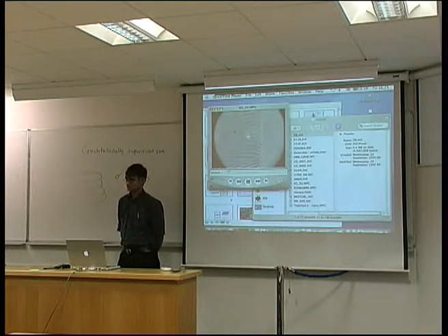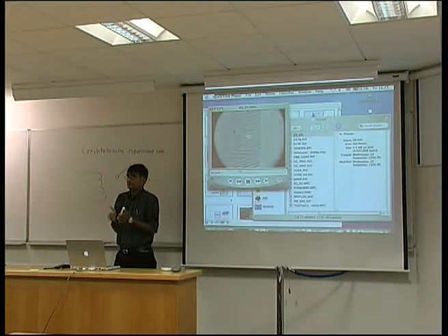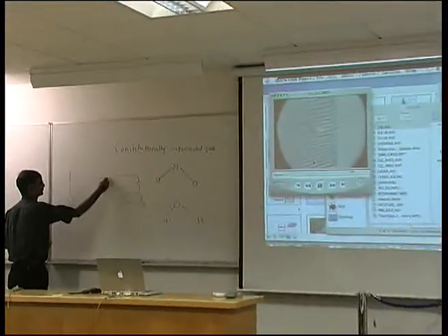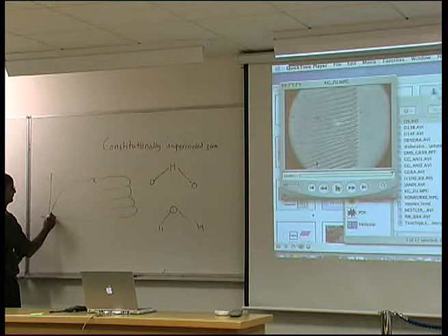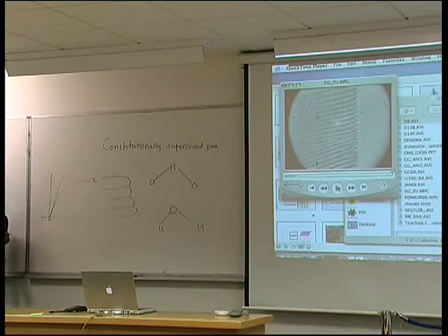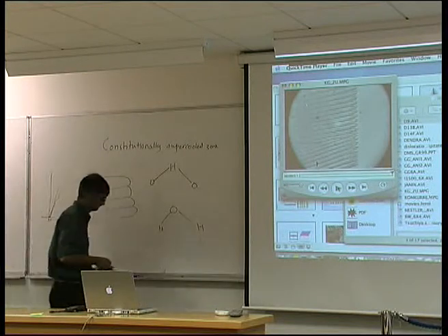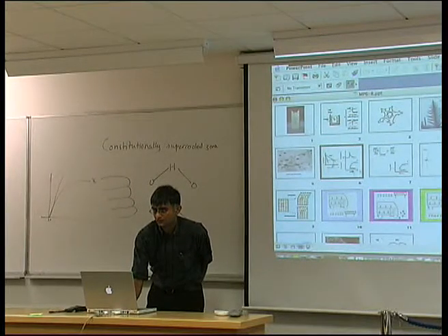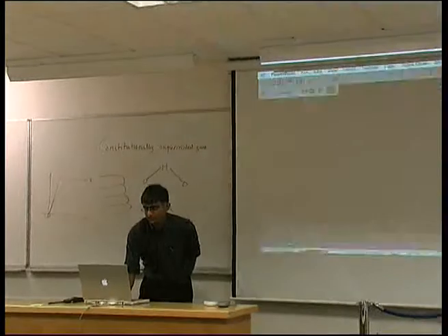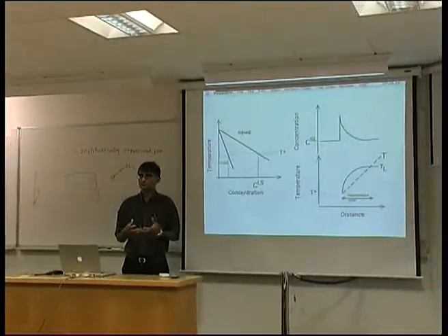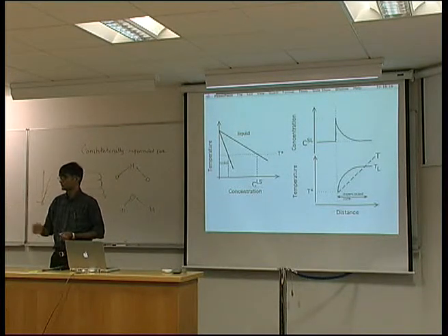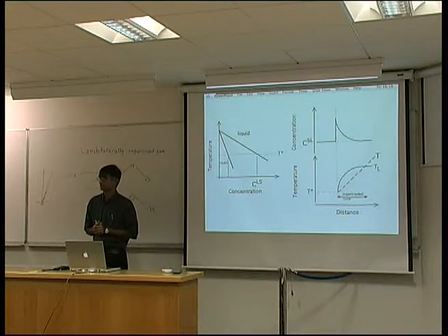So this is what you call cellular solidification, where the dendrites don't really have much room to behave in an unstable manner because the constitutionally supercooled zone is quite small. That's the supercooled zone. So in this case, we are developing different morphologies. Morphology means shape of crystals, because of the variation of the freezing temperature as a function of solute concentration. You happy with that?